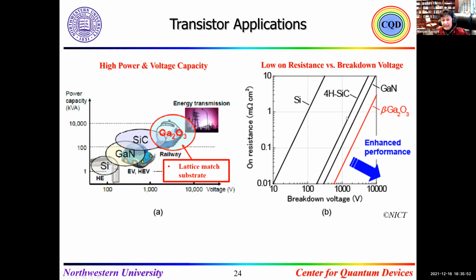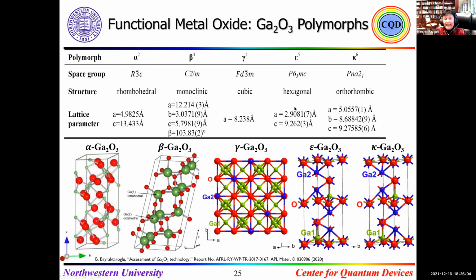If we look again at the Baliga parameter, which is important for transistors, gallium oxide is much better than gallium nitride, silicon carbide, or silicon. Not only that, but each phase has different symmetry, and each has different physical properties that I'm describing.